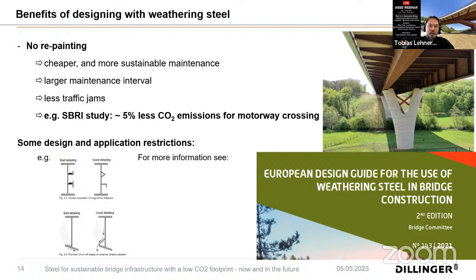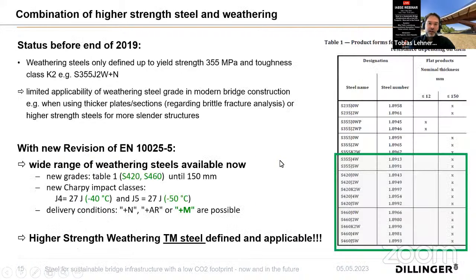There are some design application restrictions needed, but these can be found in the new European design guide. So it is already readily available to use these weathering steel grades. In the past, the usability of weathering steel grades was quite limited, because there were just limited steel grades available. So let's say the steel strength was limited to only S355 steels, but also the toughness levels were limited. So especially bridges where you need maybe higher strengths or higher toughness levels were not possible in weathering steel grades. But with the new revision, this is no problem.